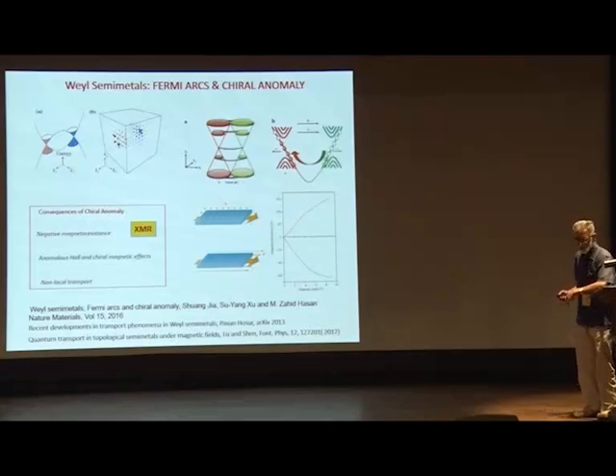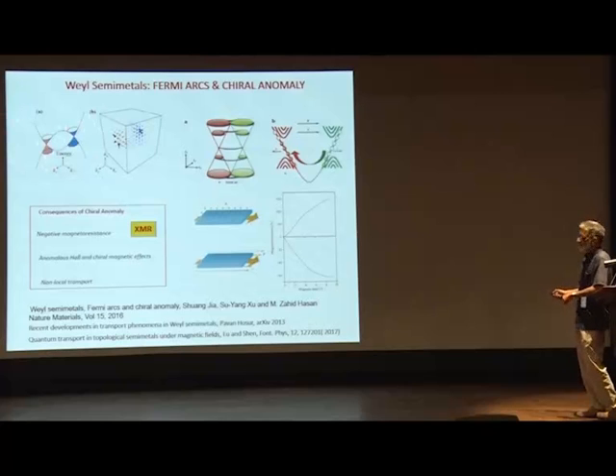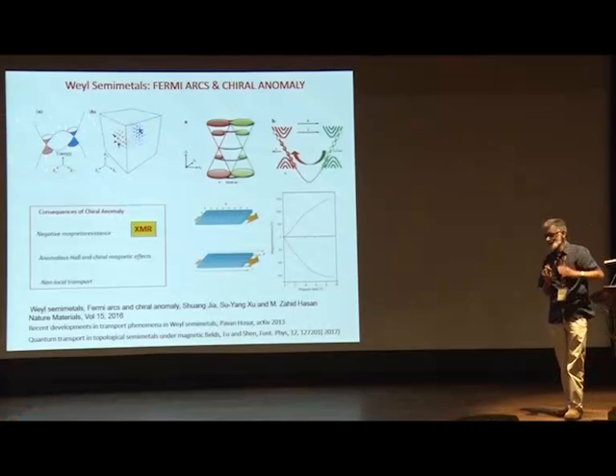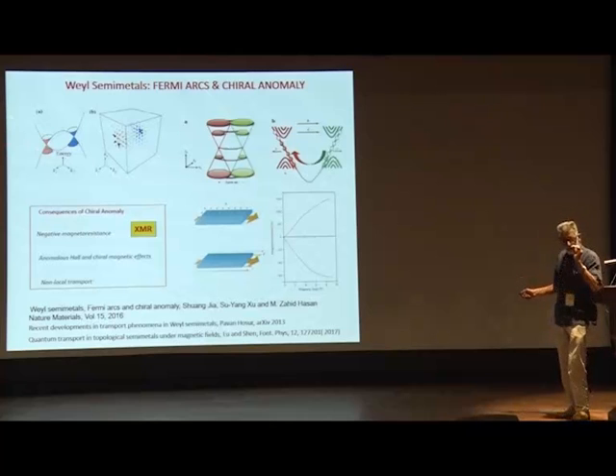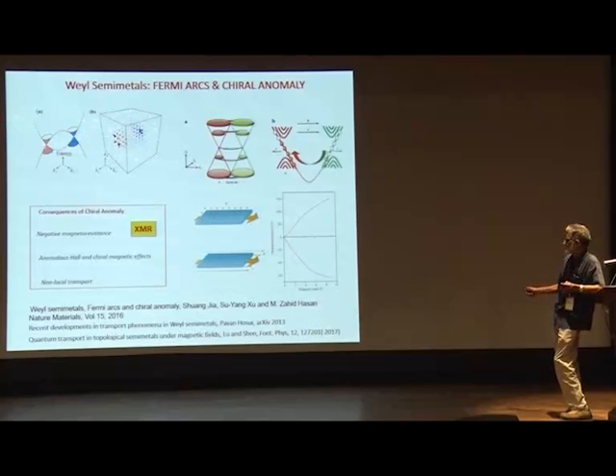Now let me switch to the other topological state of matter: the Weyl semi-metal. In a topological insulator you have a gap, but in a Weyl metal the bulk bands touch at two points — called Weyl nodes — where two non-degenerate bands are touching. These nodes have a chiral character, as shown by the Berry field distribution going from one Weyl node to the other.